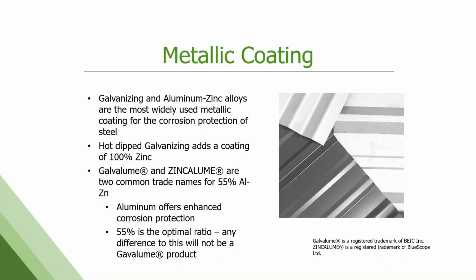So metallic coatings, I want to talk about real quick. There are whole courses just on this. It's a subject unto itself, but the two typical metallic coatings that we see in coated steel are galvanized and aluminum zinc. Galvanized is a 100% zinc coating. It has to be added so that the steel doesn't rust. And then the aluminum zinc, 55% aluminum zinc, is commonly known as Galvalume or Zincalume in the industry. The addition of aluminum provides really enhanced corrosion protection. 55% has been determined the optimal ratio for that.